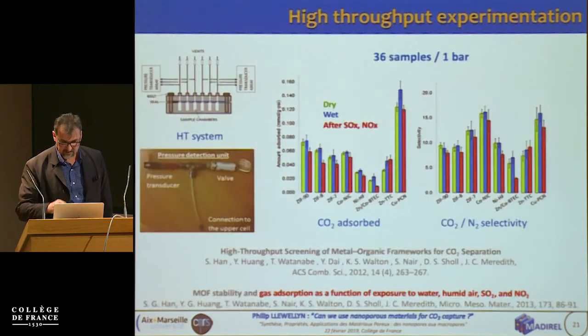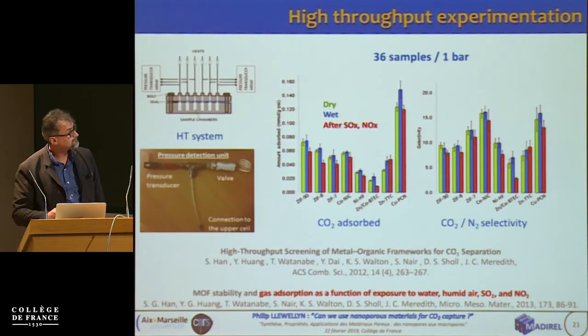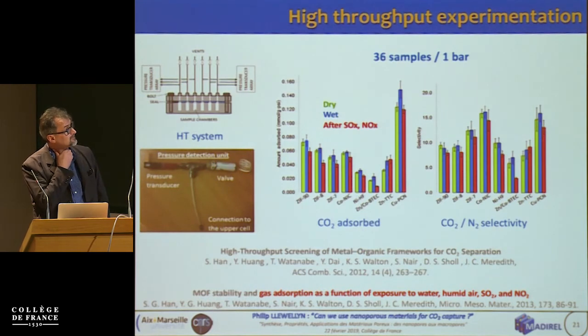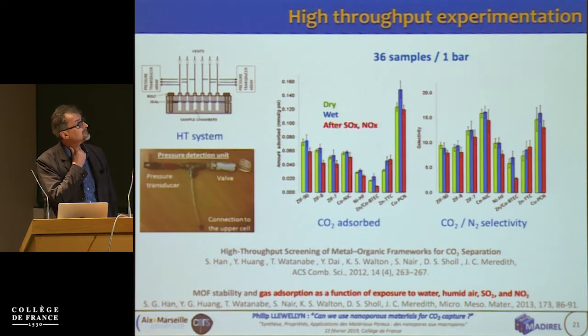What other people have done is taken this further and looked at the CO2 uptake and the selectivity of CO2 over nitrogen in the dry state, the green lines, in the wet state, the blue lines, but also after treatment in SOx and NOx to see whether the materials degrade. And so that is also of interest in a way of screening. There are also high-throughput experiments to look at other contaminants.